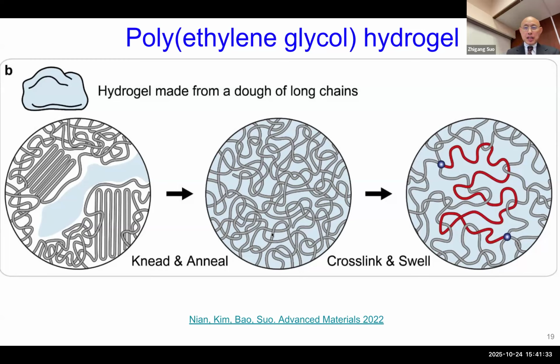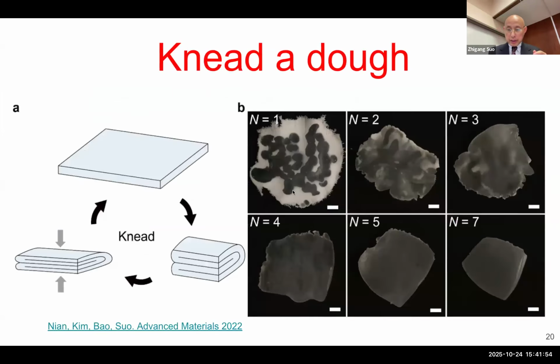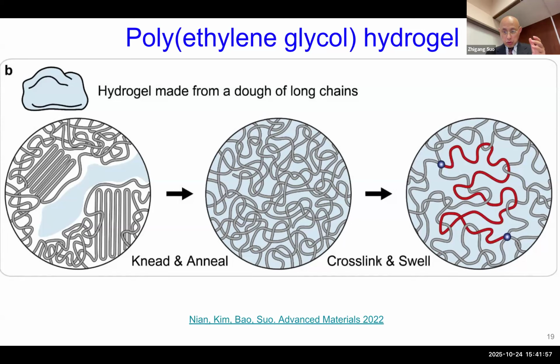This is knead and anneal. The anneal step allows the chains to entangle together. Again, the reason you want very little water is because you want polymers to be very crowded, able to entangle by thermal motion. After that, you do crosslink, and then you put it into pure water to swell to equilibrium. That way, you prepare long chains and lots of entanglements. You prepare high-entanglement PEG, the Tanglemer.